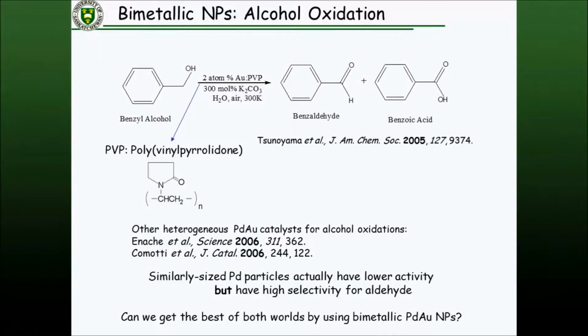The first thing we started to do was we saw a paper in 2005 from a Japanese group, and they were using polymer-stabilized gold particles for the oxidation of alcohols to aldehydes and a little bit of benzoic acid and its ester. This was in water, so solution chemistry, with a little bit of base, and polyvinylpyrrolidone again used as the polymer stabilizer.